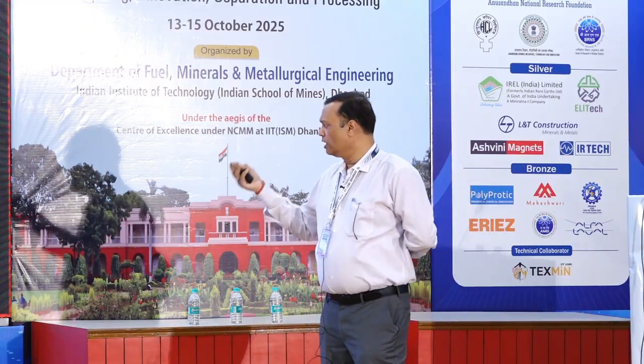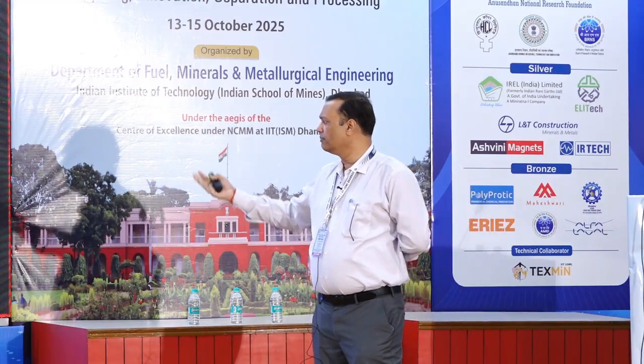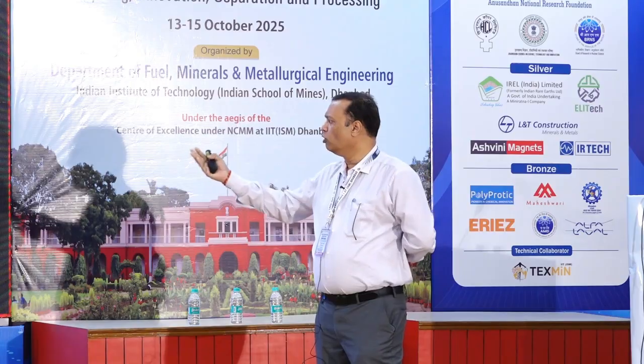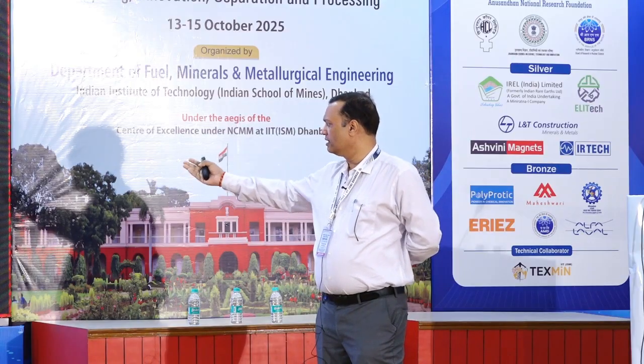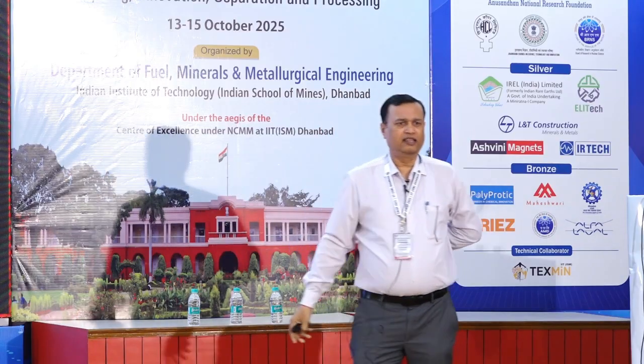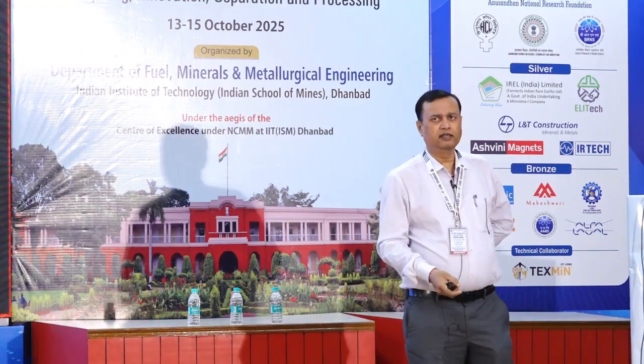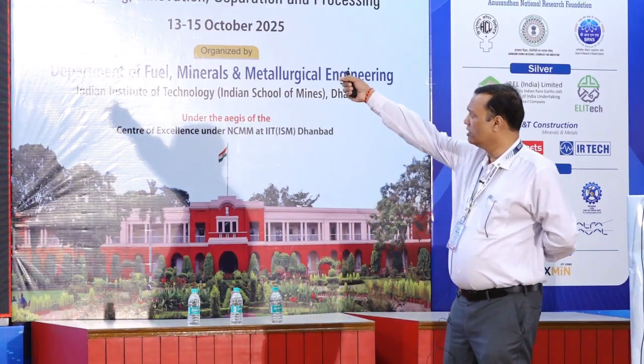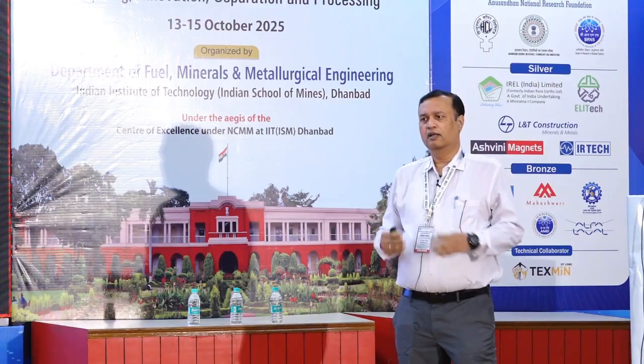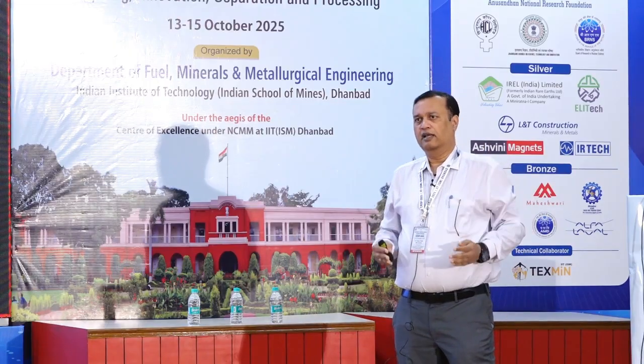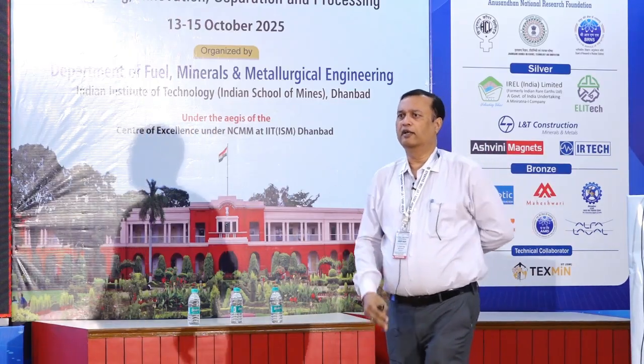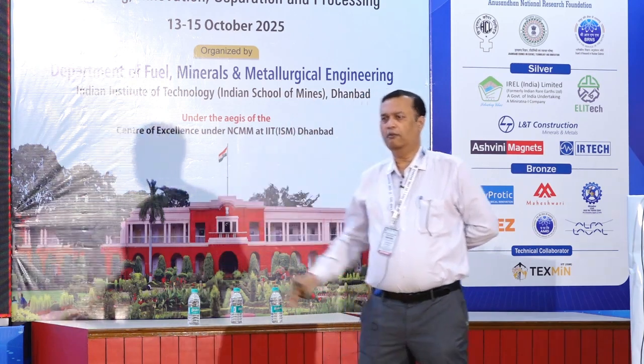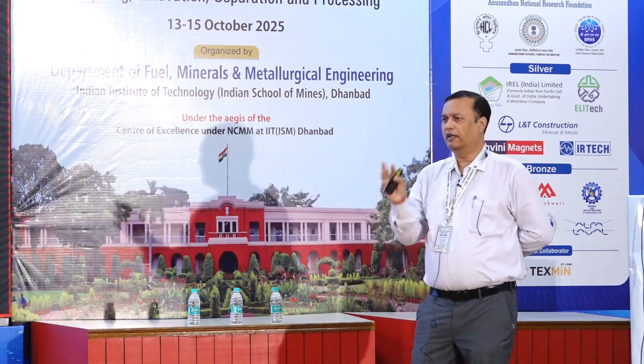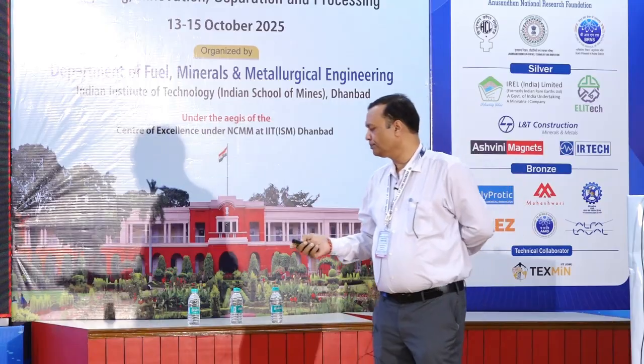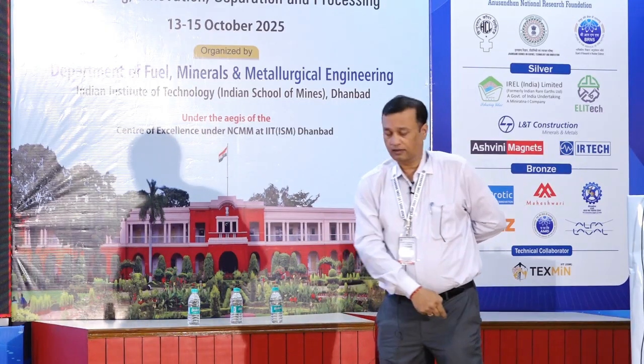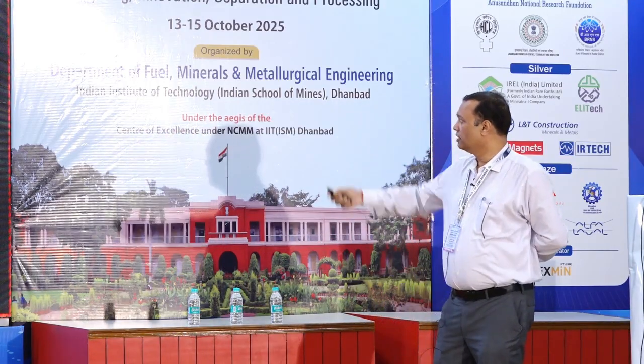So you can see that there are several elements in the periodic table which can go directly to the grain boundary, such as gallium, copper and aluminium. These are basically low melting point elements, and when they reach the grain boundary, they further lower the melting point of the Nd-rich phase. Because of this low melting point, it can easily encompass the grain and separate each grain from the other grain. So this is what happens.